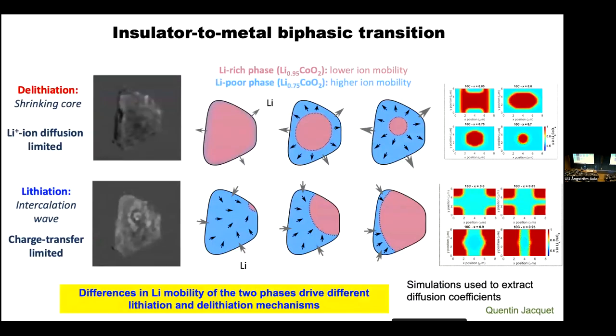And then lockdown happened. So my former postdoc, Quentin Jacquet from Jean-Marie Tarascon's group, had plenty of time to learn how to do continuum modeling. And so what he did was to model these two phenomena and examining, again, two phases, one that has very high lithium mobility, which is the delithiated phase, and the original lithium-rich phase, where the lithiums are essentially stuck. And then you can start to rationalize why this happens.